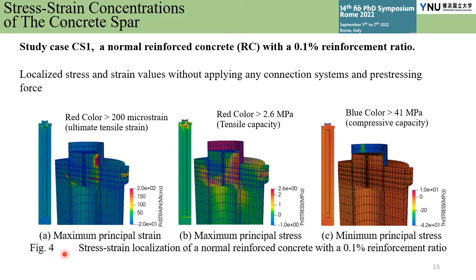For a normal concrete, if the tensile strain in concrete is greater than the ultimate tensile strain of 200 microstrain, microcracks start to generate. Therefore, the red area in figure A is the critical area that must be strengthened to control crack development. Figure B presents the principal tensile stress. Although the red zone was higher than the concrete tensile capacity, this stress can be transferred by the reinforcing bar.